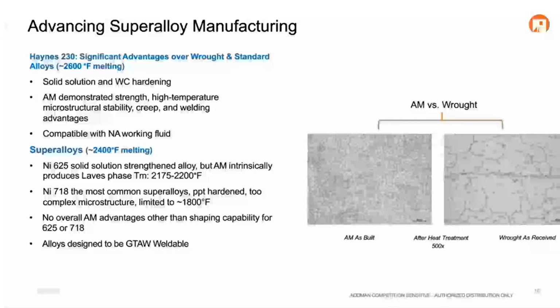When we look at the microstructure of the printed material over the wrought material, this is one of those instances where if you look in the materials handbook for Haynes 230 and the regular wrought microstructure, you kind of see just one story. But with additive manufacturing, in laser powder bed fusion especially, we've really been able to reinvent this alloy because we pick the right chemistry and get the right strengthening mechanism.